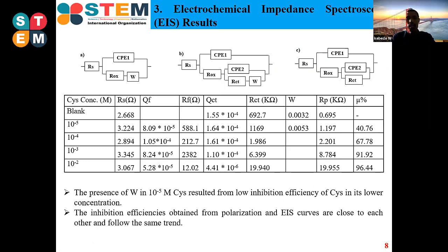And also we can calculate the inhibition efficiency using resistance: the resistance of the film, the solution resistance, the charge transfer resistance, and there is Rp, the polarization resistance.